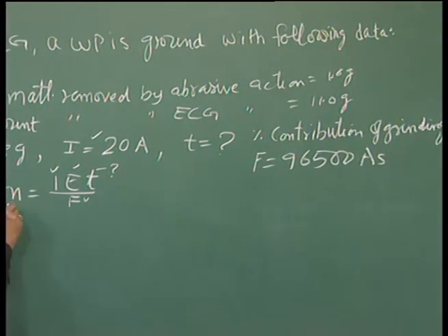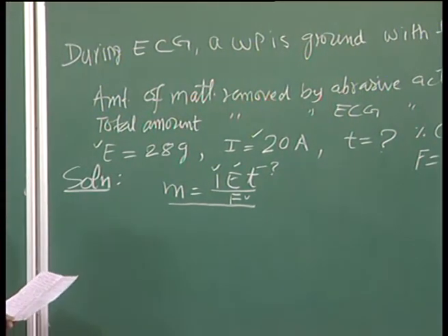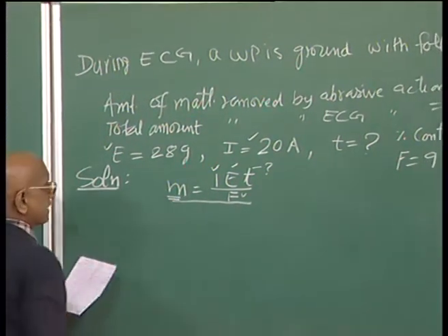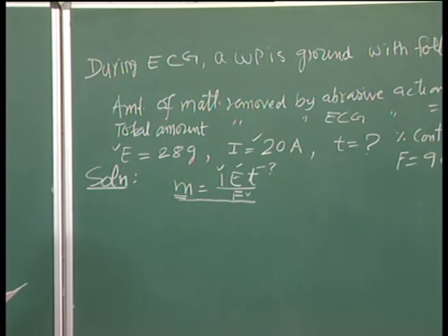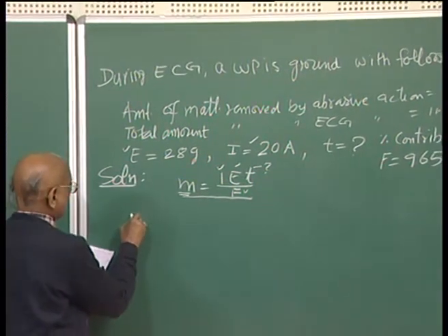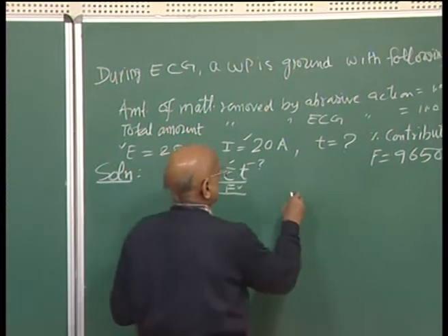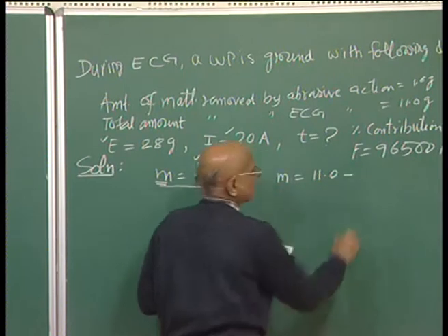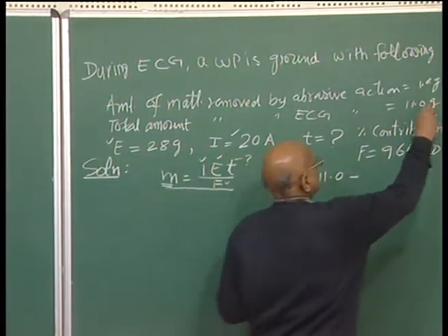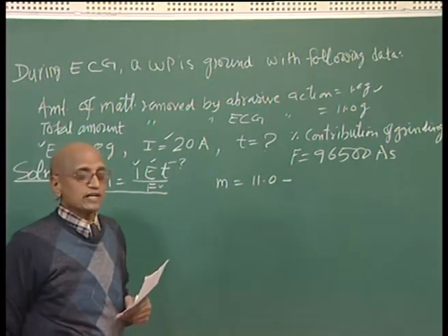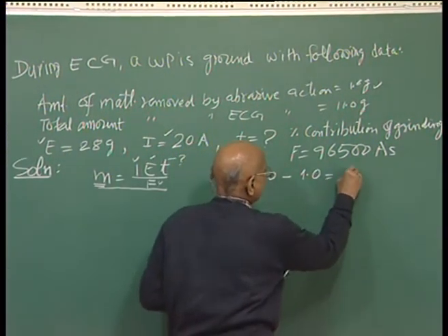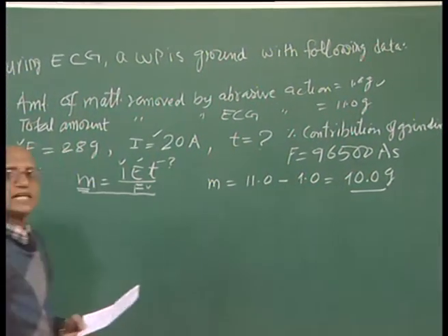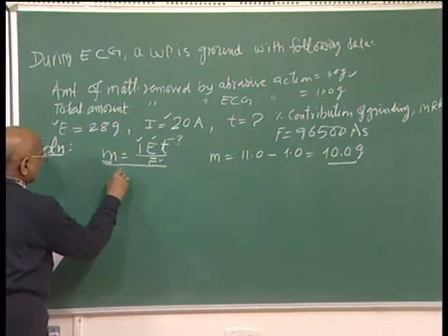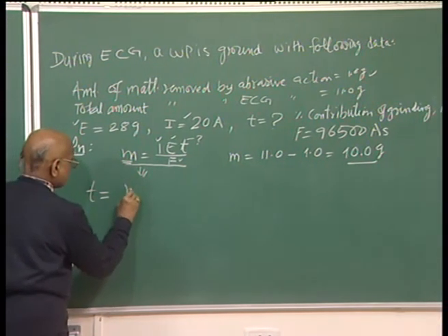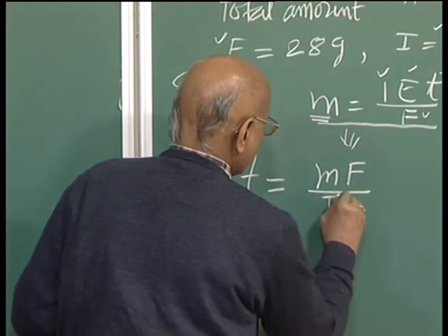Now, let us use this formula for finding out the time. Now, this M is the electrochemical dissolution contribution to total ECG. So, what is the value of M? M is equal to 11 gram, the total material removed in electrochemical grinding, minus 1 gram, the amount of material removed due to the grinding operation or abrasive action. So, it becomes equal to 10 gram as the contribution of electrochemical dissolution in the electrochemical grinding process. So, from here we can write T is equal to M F divided by I E.